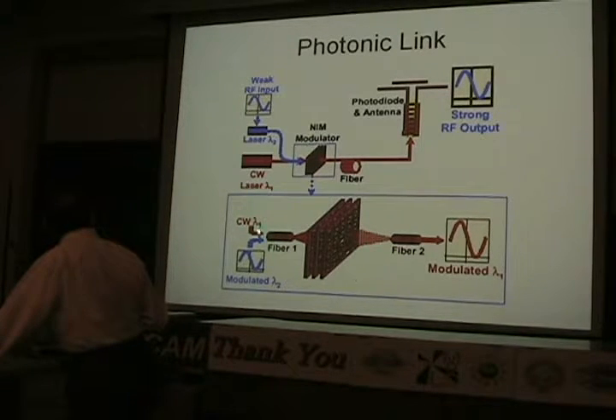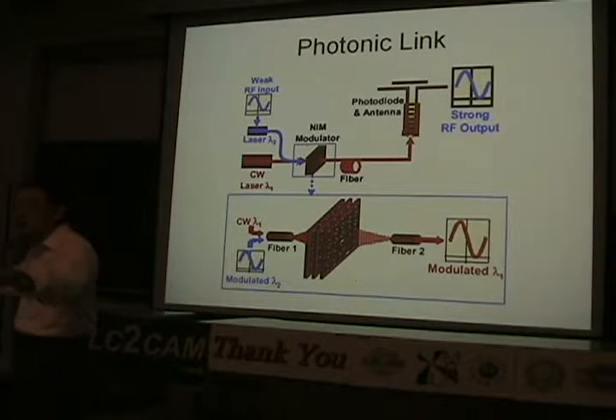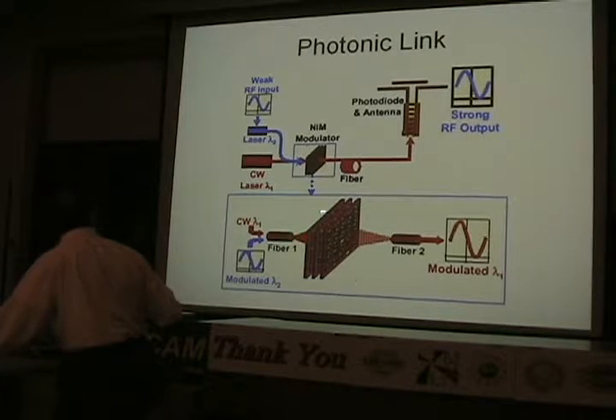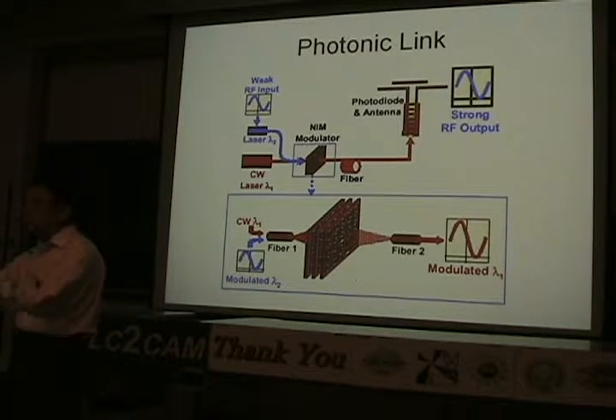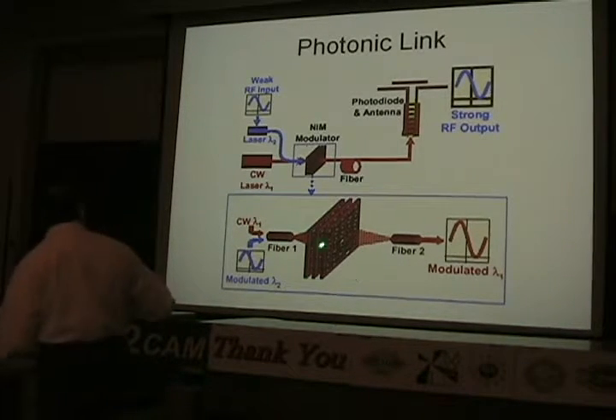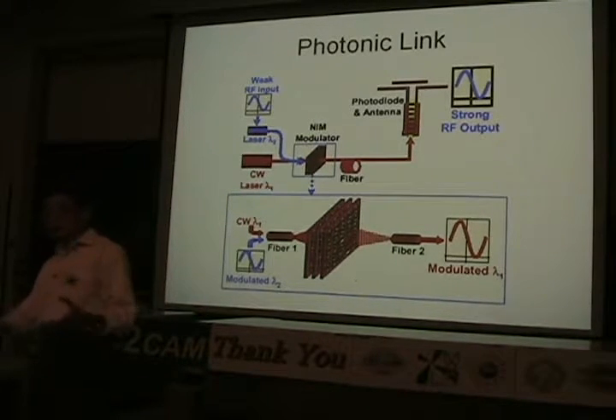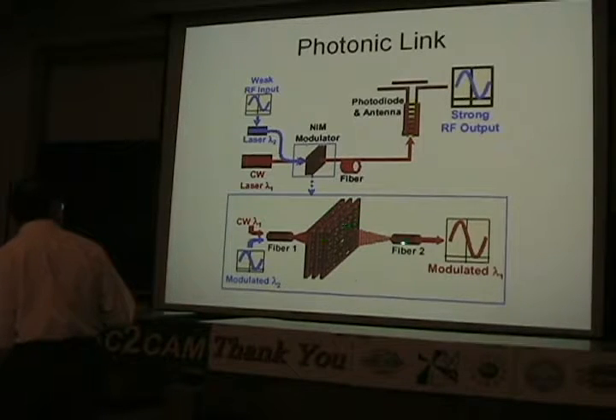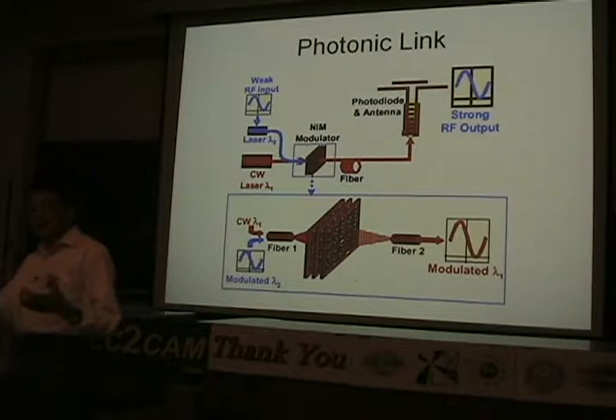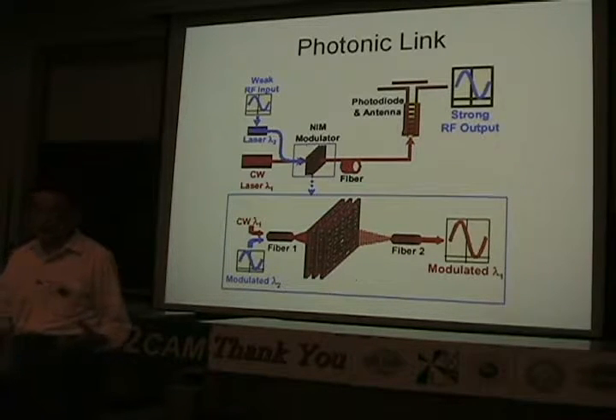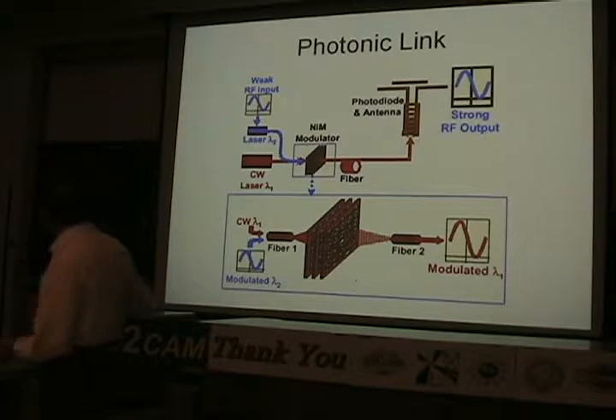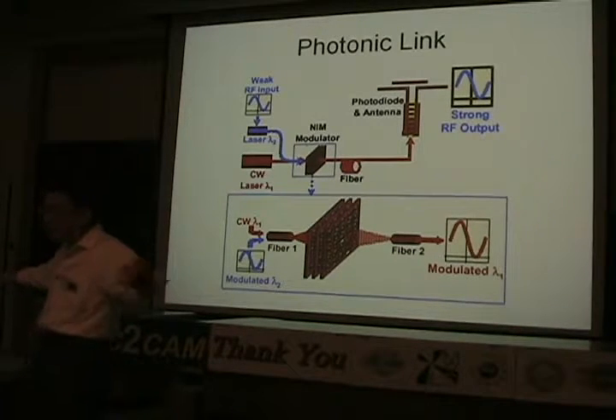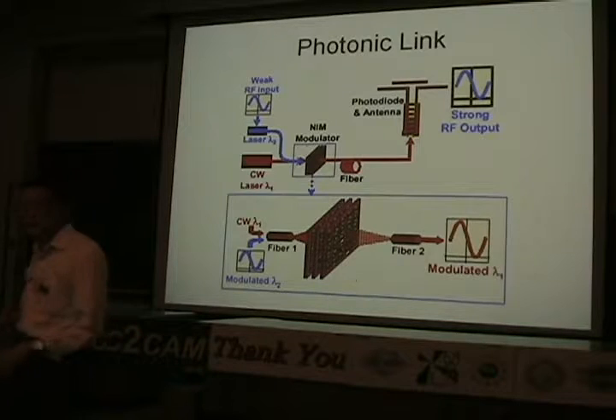You can have the optical fiber coming in, and outside it starts to diffract. And as it diffracts, it will distribute the power over this entire panel. And that entire panel is the superlens. And then you can see it will refocus. By doing so, you will have no nonlinear optical effects because the power has been redistributed over a big area and the intensity becomes small.